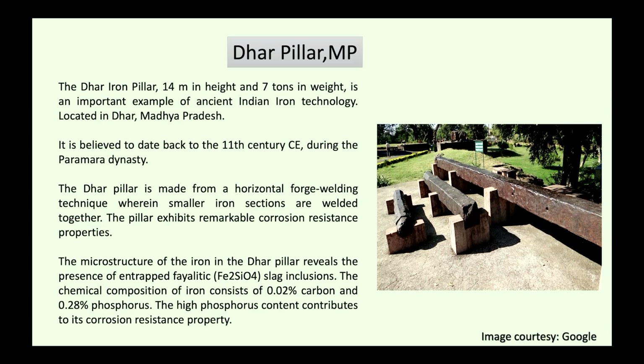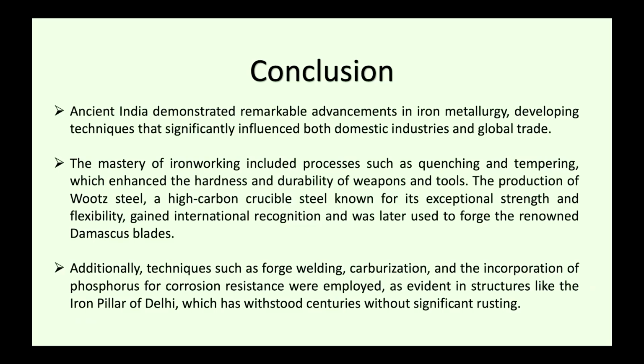The microstructure of the iron in the Dhar pillar revealed the presence of entrapped fayalitic (Fe2SiO4) slag inclusions. The chemical composition of iron consists of 0.02% carbon and 0.28% phosphorus. The high phosphorus content contributes to its corrosion resistant property. So, on the basis of the technological terminology and the examples, we can say that ancient India demonstrated remarkable advancement in iron metallurgy, developing techniques that significantly influenced both domestic industries and global trade.